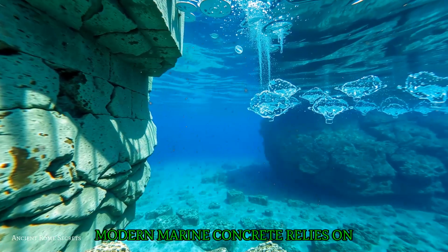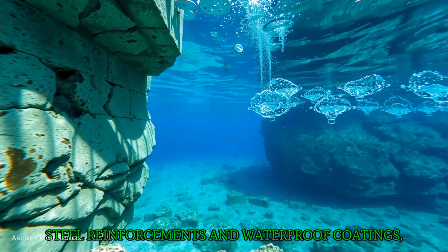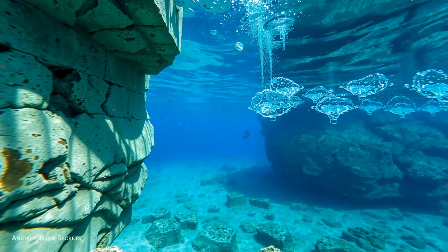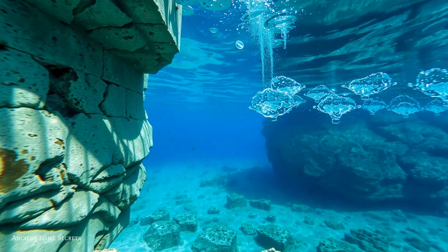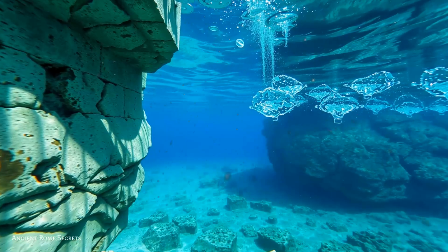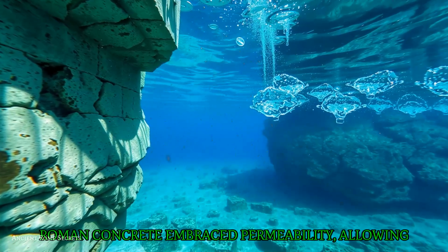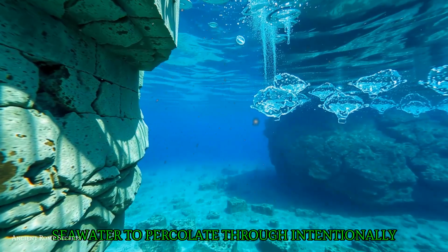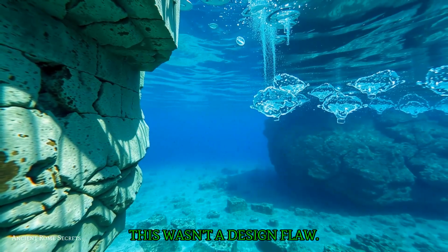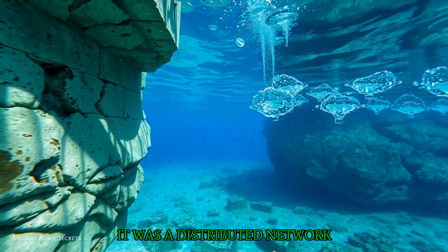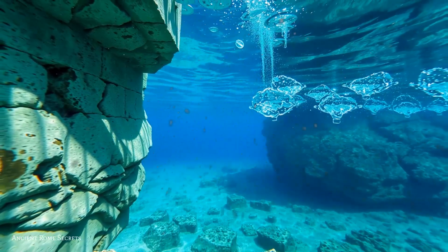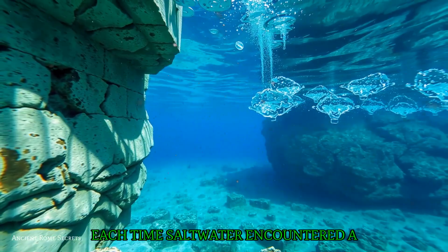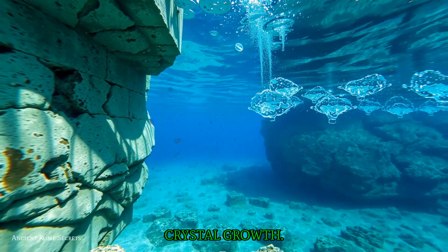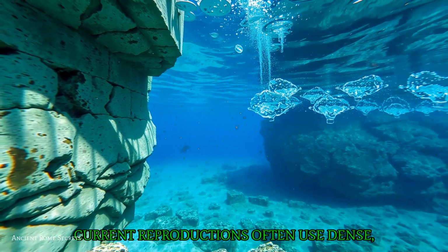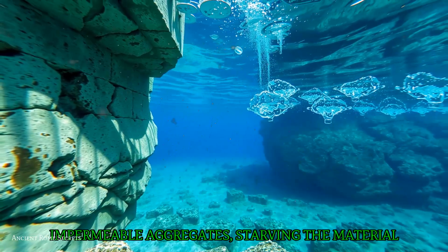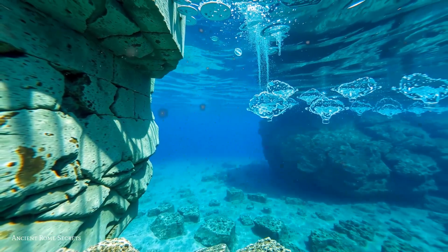Modern marine concrete relies on steel reinforcements and waterproof coatings, creating a brittle dichotomy. Either water stays out completely or the structure fails catastrophically. Roman concrete embraced permeability, allowing seawater to percolate through intentionally porous aggregates. This wasn't a design flaw, it was a distributed network of mineral factories. Each time saltwater encountered a limeclast, it sparked new crystal growth. Current reproductions often use dense, impermeable aggregates, starving the material of this chemical dialogue.